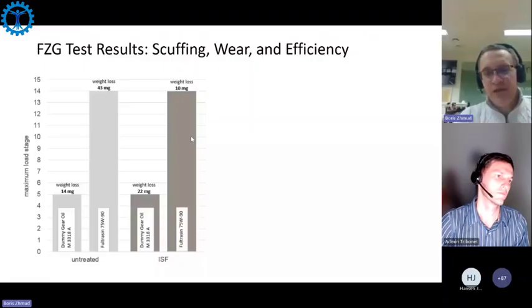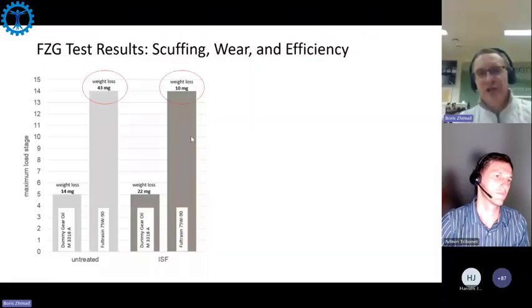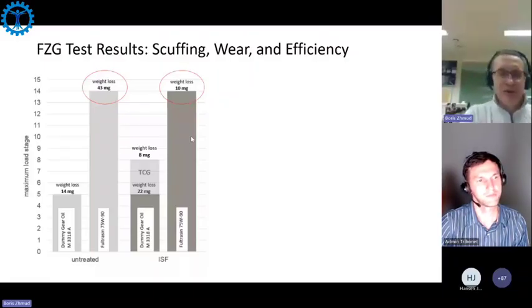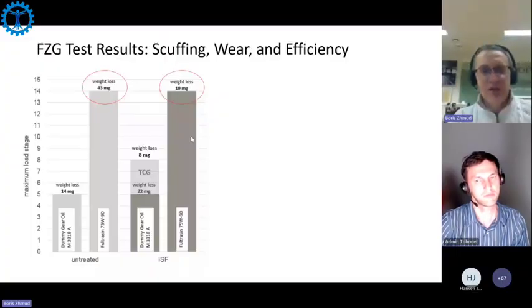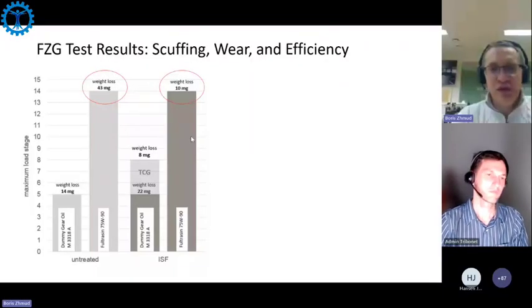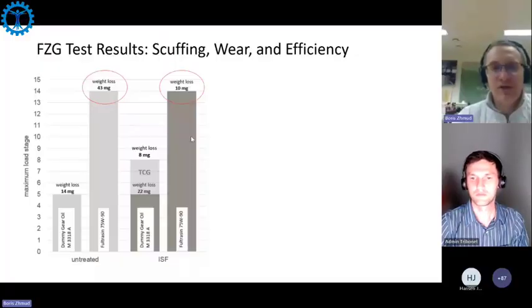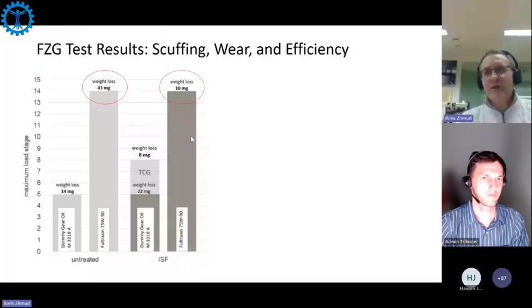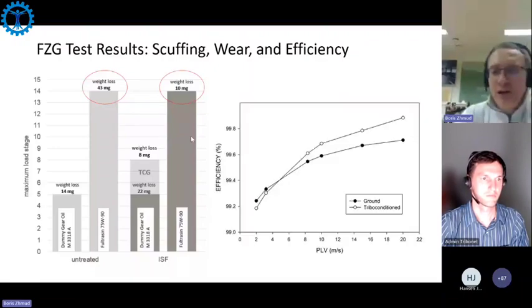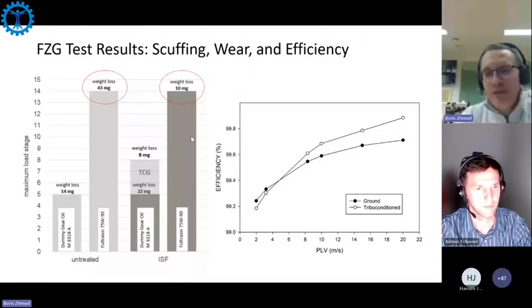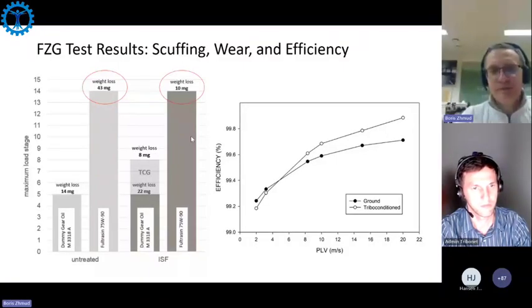What is the advantage of mechano-chemical finishing? With mechano-chemical finishing, you actually get a higher failure stage already with oil which has no additive. So basically, mechano-chemical finishing lets you take some elements of running in into the manufacturing stage, and the gear is more resistant to scuffing than a gear which was just super finished when you have no anti-scuff additive in the lubricant. And efficiency-wise, mechano-chemically finished and super finished gears have comparable performance improvement. Sometimes mechano-chemically finished gears give a slight improvement over conventional super finishing.